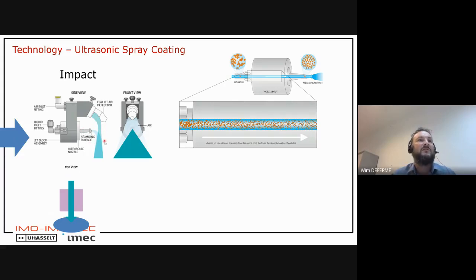You can optimize that. For example, besides the impact and the AccuMist nozzle, which was for really fine structures, we also have a vortex nozzle where you create droplets in all directions. If you look at those two systems, the droplets go perpendicular towards the substrate, so they always land at 90 degrees onto the substrate. With this vortex nozzle, you can also have droplets coming from different angles, which can be beneficial, for example, if you want to coat a rough surface.